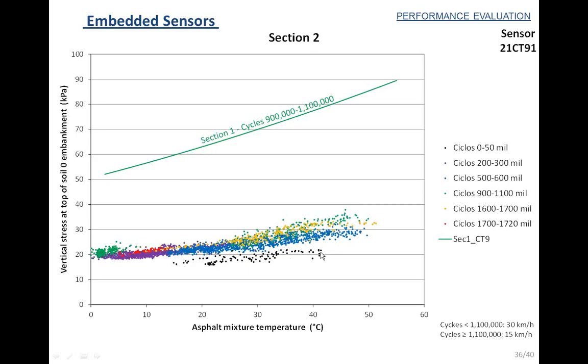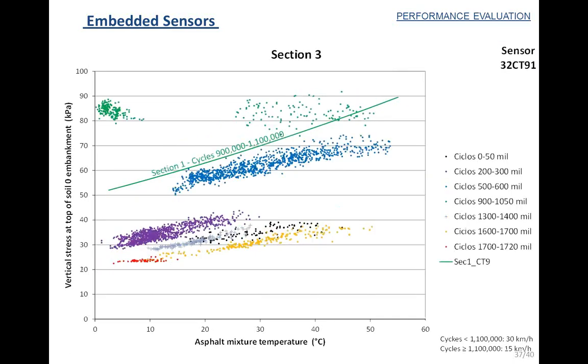Again, you can see here the stress level corresponding to the beginning of the test, and you can see here the evolution during the test. And you can see that the vertical stress is almost constant during the test. But for section number 3, the performance was very different. Again, you can see here the black points. These black points correspond to the beginning of the test, and you can see here the evolution during the test.